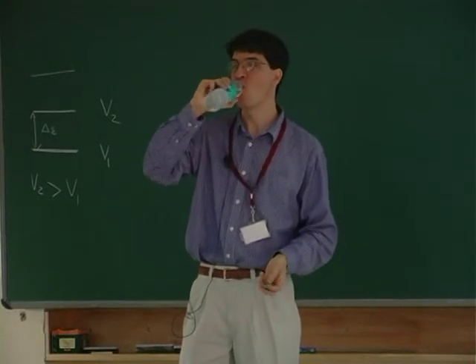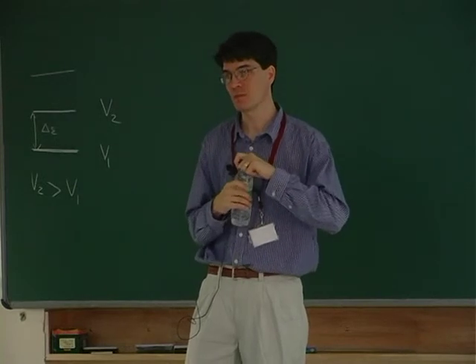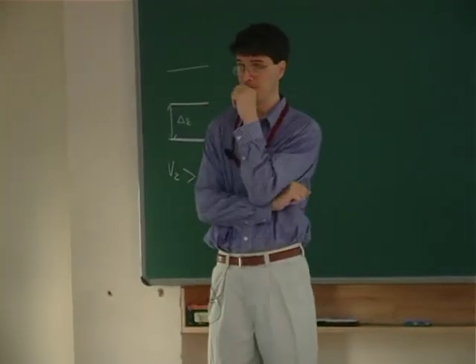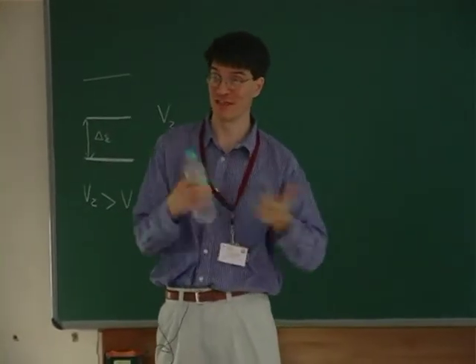Just a quick comment on the early part that you pointed out, the interface stretching and contraction, and expecting the volume to be conserved by changing the bond length in the perpendicular direction, which doesn't quite happen. But this concept of chemical pressure, by substituting a larger or a smaller atom, you can see the unit cell changing very systematically in X-ray diffraction. It turns out that even in that case, the bond lengths are not changing at all. What is changing is the angle. This is a mismatch between the way we probe with X-rays, looking at the long length scale of the structure, and the microscopic length scale of the bond lengths, which don't change at all. The change that you see over a long length scale is actually accommodated by the angle change, which you often don't appreciate. That is also why it's important to study bulk materials as well as film materials. Exactly, because then you can learn from both.